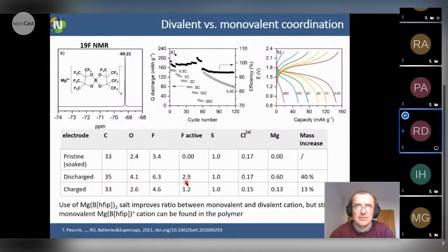So there was a recent publication from a United States group where they claim that using different salts, maybe this boron hexafluoroisopropyl compound can solve that problem, but we have recently published a paper in Batteries and Supercaps that this is not really the case, that even if you are using this type of salt, which weakly coordinates magnesium cations, we can still find some HFIP inside the organic polymer structure. So that means that we still have a co-insertion of a monovalent magnesium boron HFIP complex.